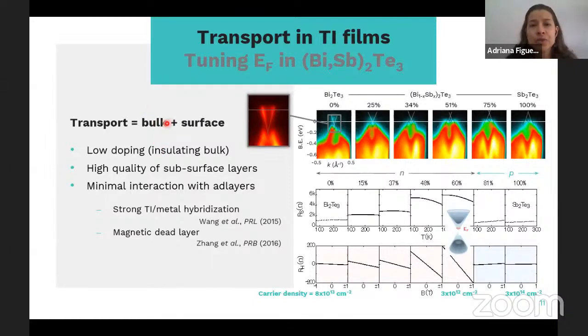So what we want to do is reduce such contribution of bulk, and that can be done by adding to bismuth telluride, for example, that is a TI, some doping of antimony atoms, so that you're able to tune the position of the Fermi energy in the gap. You make sure that your material is insulating, and then the transport is mostly done by the surface states of the TI, and that is obtained at a concentration of about 60%.